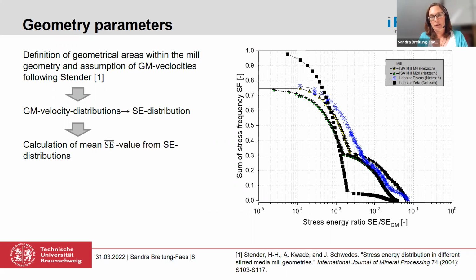And when you compare the results with each other, you can see that at least the 3 mills with the discs look very similar. They have a similar geometry, and so the distributions look very similar. What also can be seen is that the curves are shifted from small grinding media volumes to bigger grinding media volumes, to smaller values. The one for the theta geometry looks totally different. So it's a totally different stirrer. And so the distribution looks different. From these curves, I calculated at least the mean values.